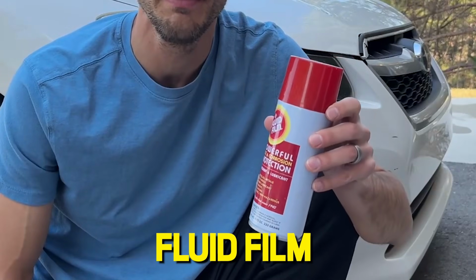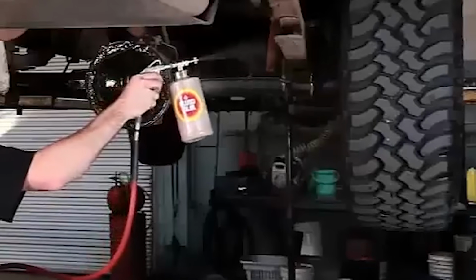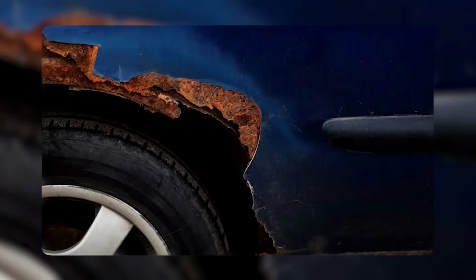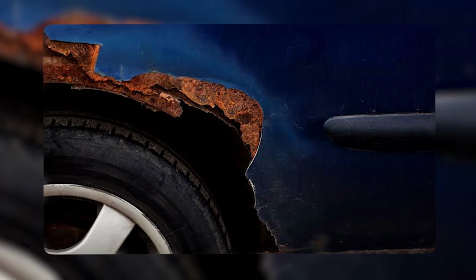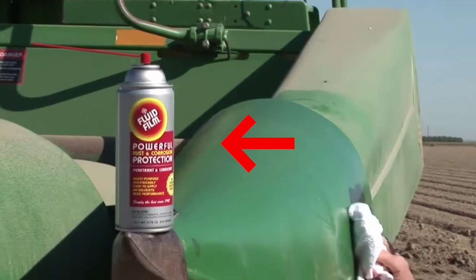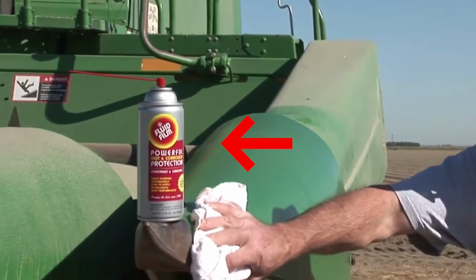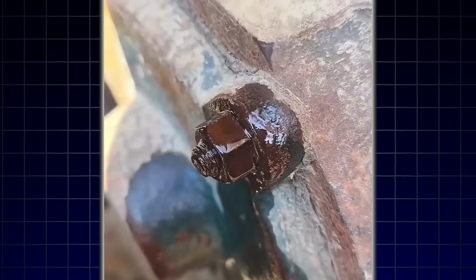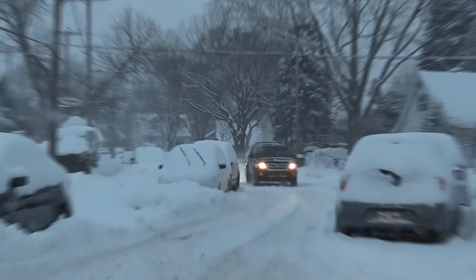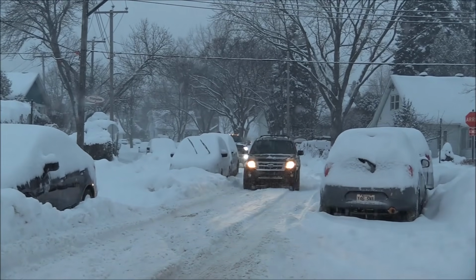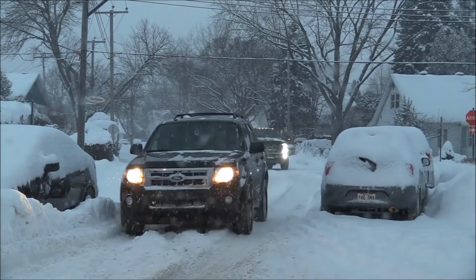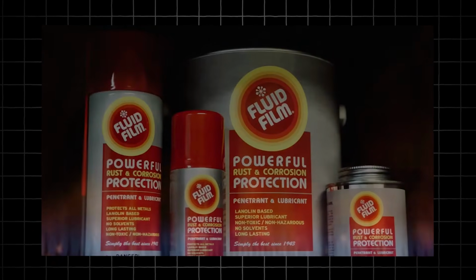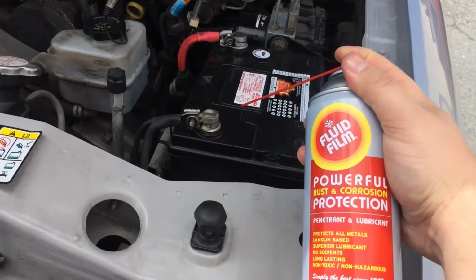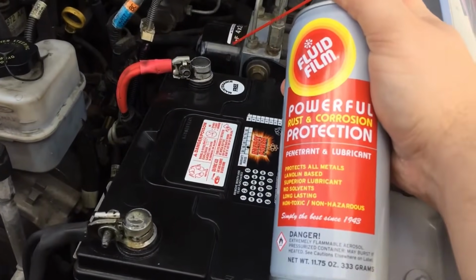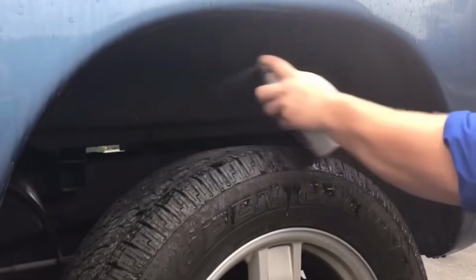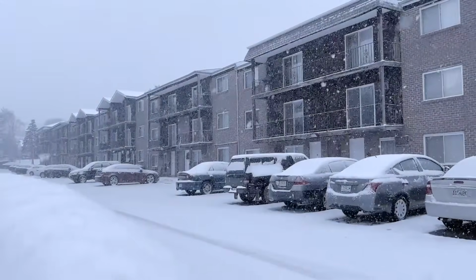Fluid film is a lanolin-based product like Woolwax, but it is formulated with a different base oil and additive package, one that specifically addresses the cold temperature brittleness limitation that disqualified Woolwax from severe winter application consideration. The formula was originally developed for military equipment corrosion protection. Cold temperature performance in that context is a non-negotiable requirement, not an optional feature. That military development heritage produced a cold weather performance profile that is genuinely different from consumer lanolin products. The formula maintains measurable fluidity at temperatures down to -30 degrees Fahrenheit.